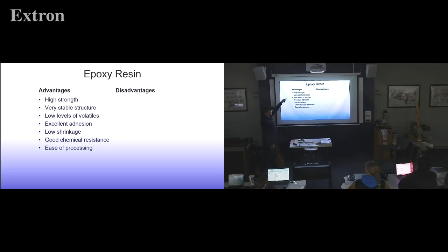High strength, very stable structure, low levels of volatiles, excellent adhesion, low shrinkage, good chemical resistance, ease of processing. I also need to note one thing that's very, very important. You can repair polyester resin projects with epoxy. You may not repair epoxy resins with polyester. You can only go the one way. And so if it's in doubt whether your piece that you are gonna try to fix was made with polyester or epoxy, what are you gonna repair it with? Who cares if it was polyester? You can always go over polyester with epoxy. You can never go the other direction.